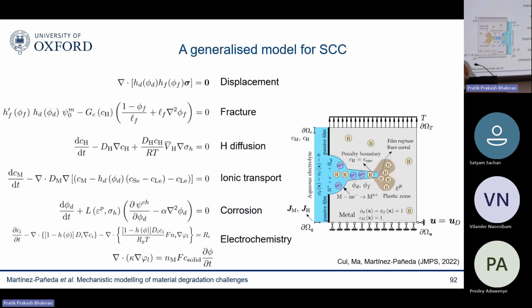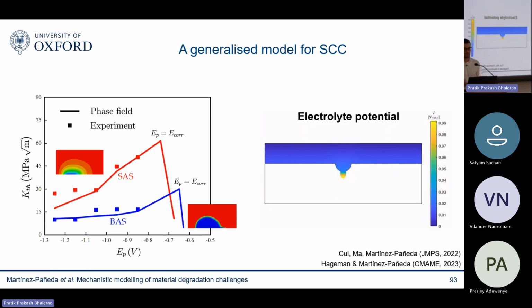And then finally, the very last slide, you can also couple this with all the hydrogen embrittlement that you had before. So you don't need to make any assumptions on whether the fracture in this stress corrosion cracking condition is going to be driven by hydrogen, by anodic dissolution, by a combination of both. You have all the physics in your model, and you let the model do the job for you. And with that, you can capture toughness as a function of applied potential for a wide range of conditions.